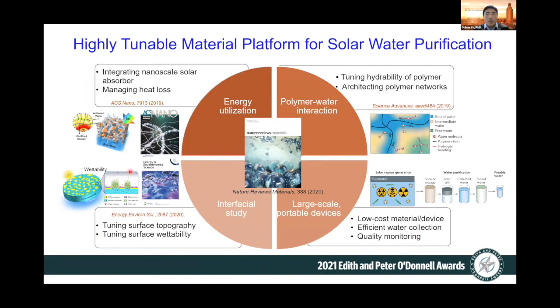And in the recent 2 years, we have expanded this direction through more systematic studies, and shown that hydrogels are very tunable material platforms for solar water purification. For example, we better understand the solar absorptive particle interaction to enable this energy nano-confinement. We also can tune the hydrophilicity of the polymer network, by changing the functional group or by selection of different hydrophilic polymers. And we also investigate different effects, for example, surface topology or surface wettability to enhance the solar vapor generation efficiency. Right now we are working to develop more prototypes, closer to usable devices, hopefully to be able to use for household needs and potentially even larger scales.